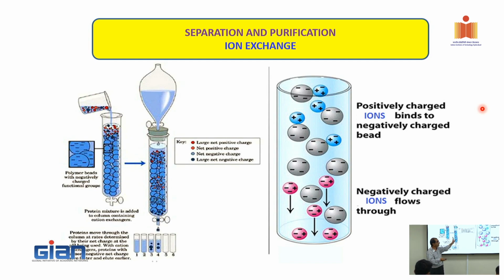During this process, two things take place. One is separation, or selective removal of the wanted from unwanted ions. The second thing is enrichment also. Suppose this leach liquor contains copper ion at, say, 1 gram per liter. You load it. Entire copper is loaded here. Say 30 grams of copper is loaded in 10 grams of resin, or some 20 grams of resin. So it is called loading capacity.